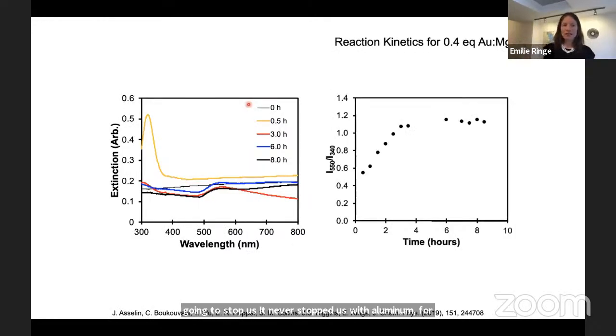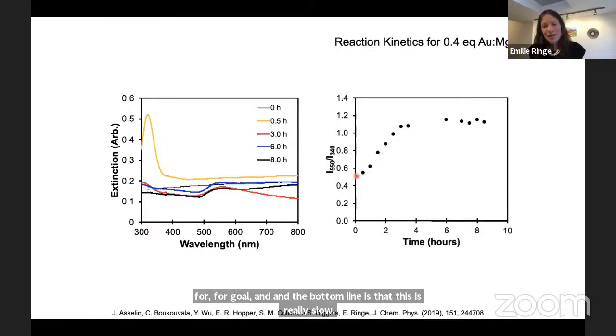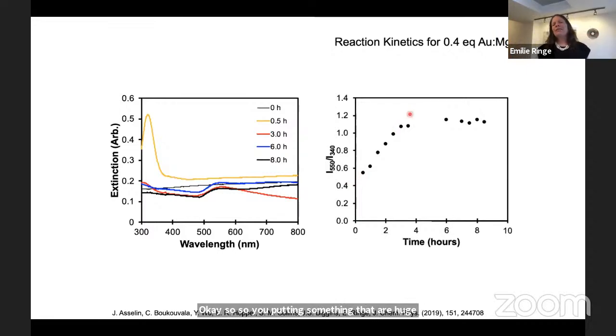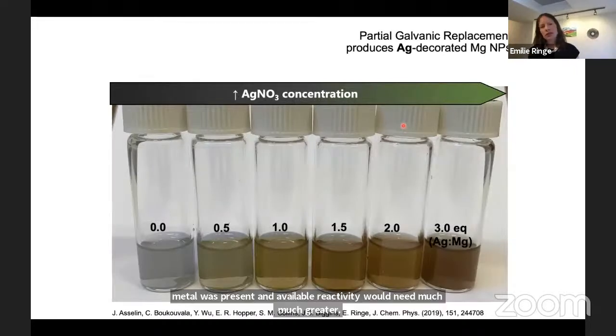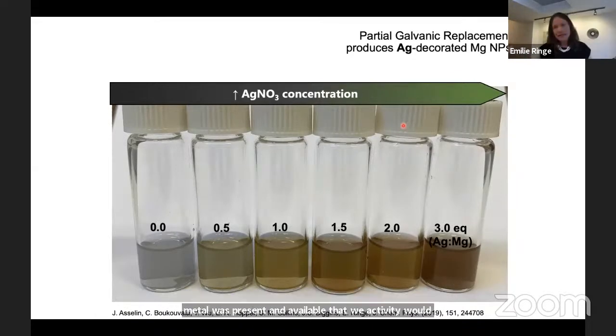The plasmonic response of gold here, that's sort of 550, allows us to follow the reaction kinetics for this. We've done this with all the other metals I'll show, but I'm just going to show it for gold. And the bottom line is that this is really slow. Okay, so you're putting something with a huge thermodynamic driving force, and it takes about 4 hours to do anything. This is just telling us that the oxide layer is slowing things down significantly in this reaction. If magnesium metal was present and available, reactivity would be much, much greater. We've now done this with a whole slew of metals, right? Magnesium will basically give electron to most anything in the periodic table.